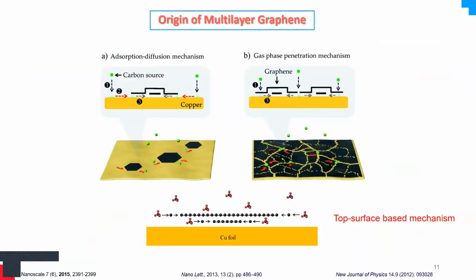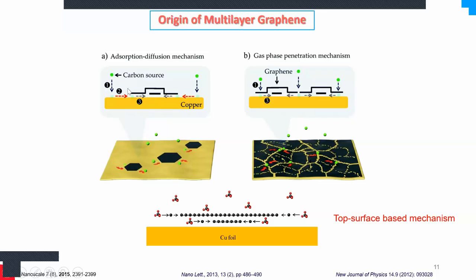So people think about graphene growth as a top surface based mechanism. What we have in the CVD is a copper foil, and the copper foil has two sides, top and back. In the literature, people mostly care about how graphene is growing on the top surface. So like you see here, the carbon source comes from the top, and it deposits or adsorbs on the surface of copper. And then once we have one layer, you can have a second layer underneath the first layer. Okay. In this way, we can end up growing multi-layer graphene. We have a top layer of graphene, and then a bottom layer as a bilayer of graphene.